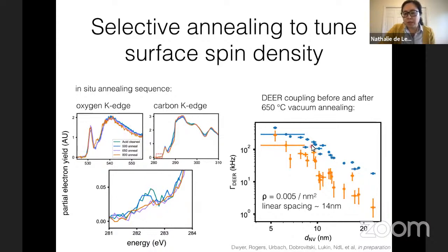And similarly, this is a much larger data set where we are looking at a bunch of NV centers in one sample, and looking at the exact same NV centers before and after, plotting this DEER signal. You can see that it gets suppressed by around a factor of 3 or 4 after we do this annealing. Okay, so this is nice.